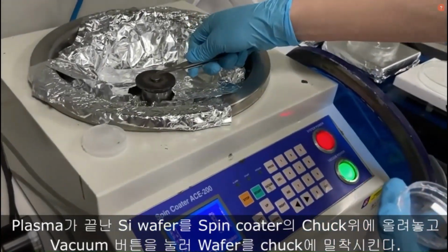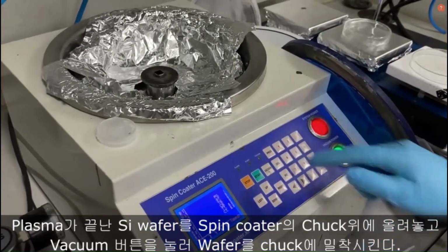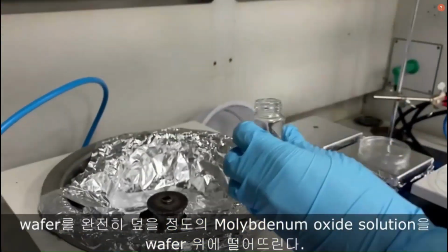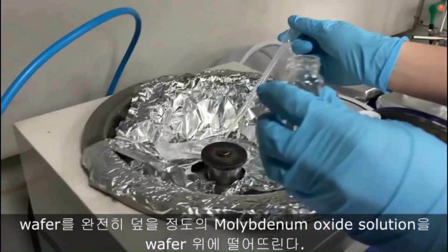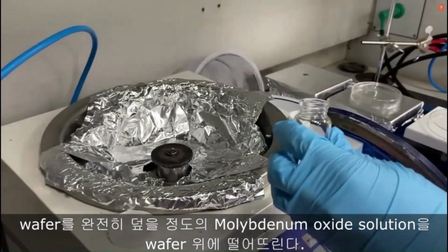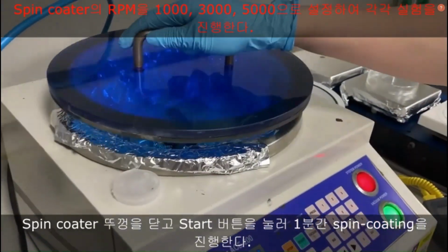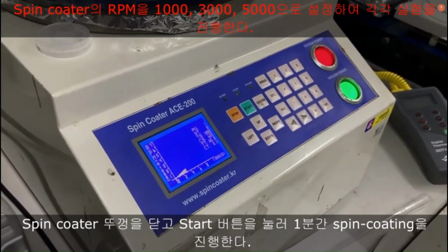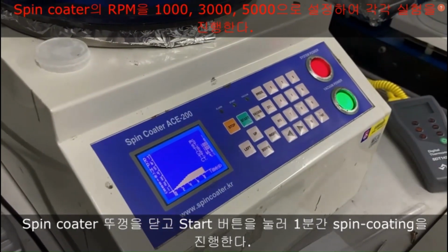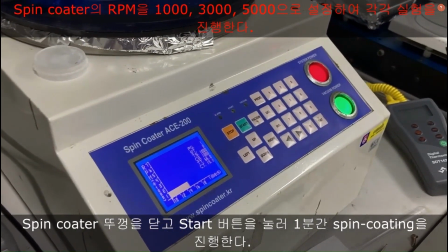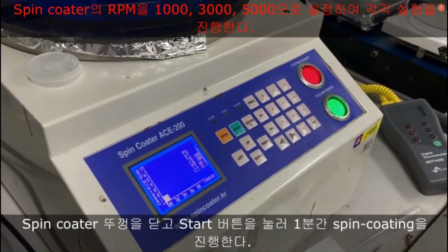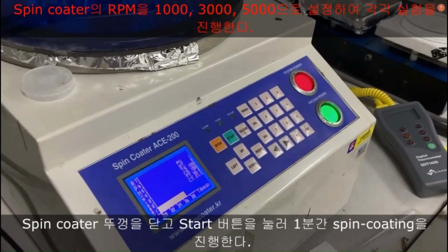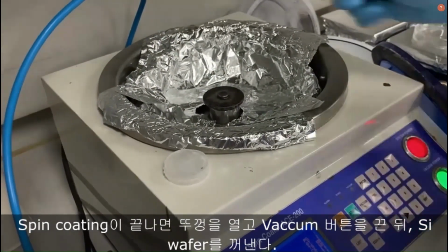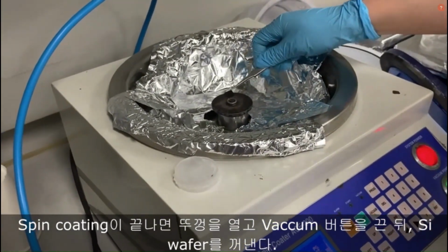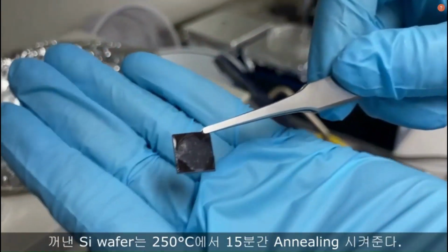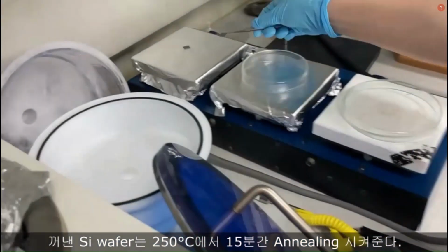Put the plasma-treated wafer on the chuck of the spin coater and press the vacuum button to secure the wafer. Then drop the dissolved molybdenum trioxide solution onto the wafer. Close the lid and press the start button to start spin coating. After the spin coating is done, turn off the vacuum button and take out the wafer. The wafer is transferred to the heating plate and heated at 250 degrees for 15 minutes for annealing.